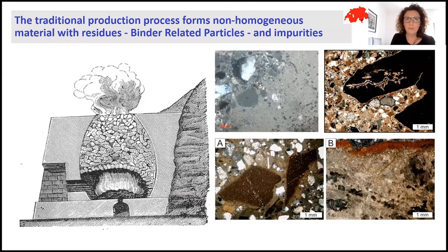This traditional production process forms a binder which is not completely homogeneous, because, as you see in this reconstruction of these kilns, we will have some stones which are very close to the fire, in the zone with the highest temperature, and then we have some stones far from the fire. In this way, we obtain different material. For example, we can have the underburned particles. These particles are called, in general, binder-related particles.